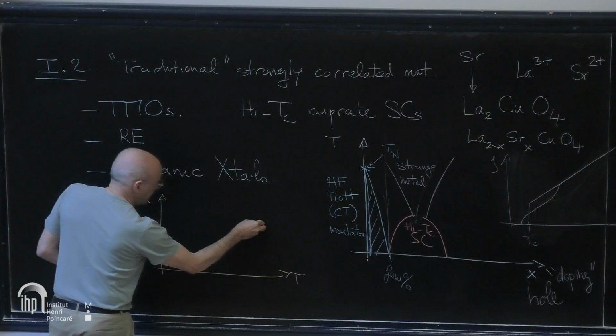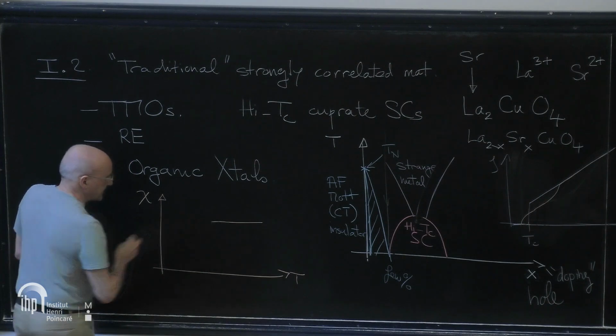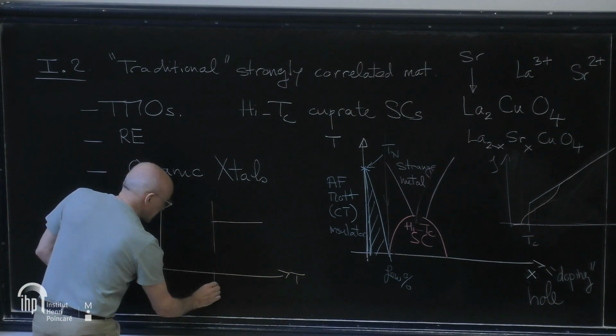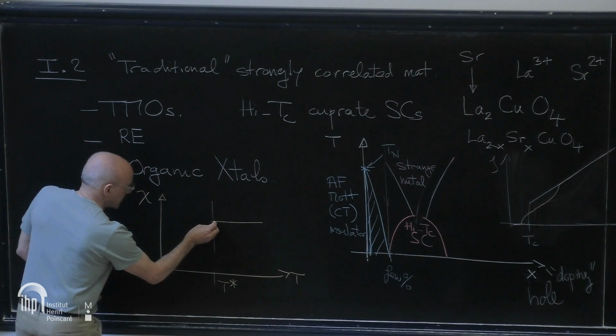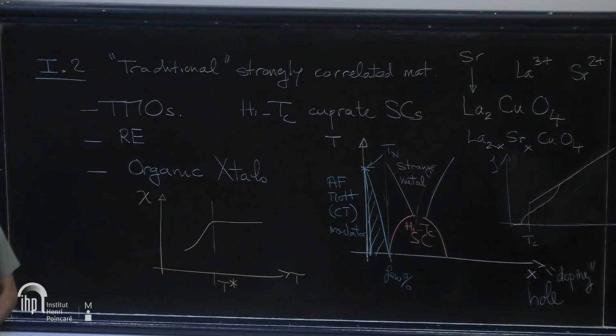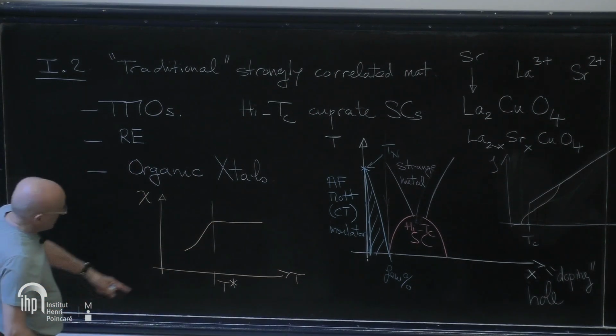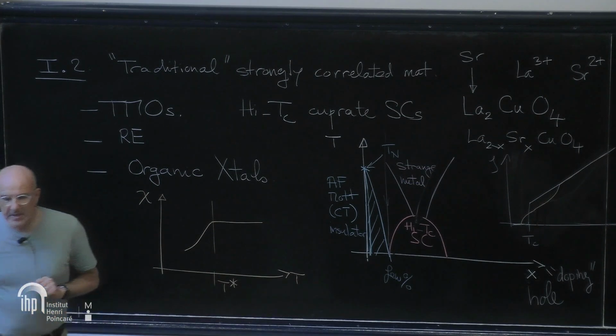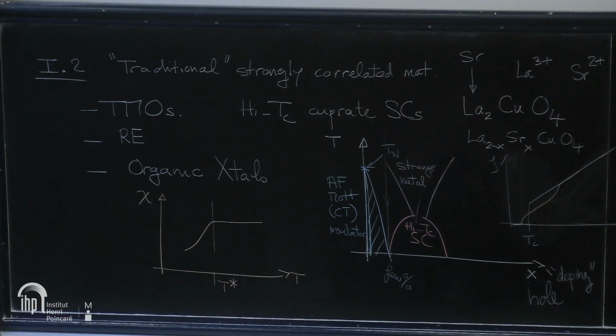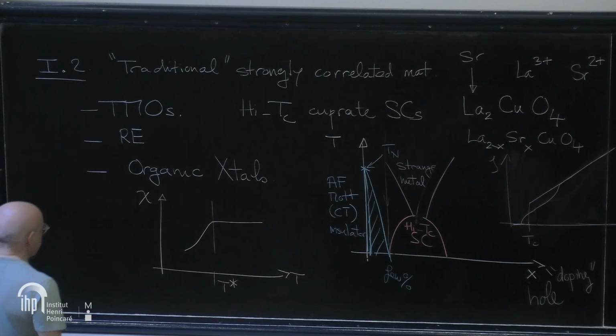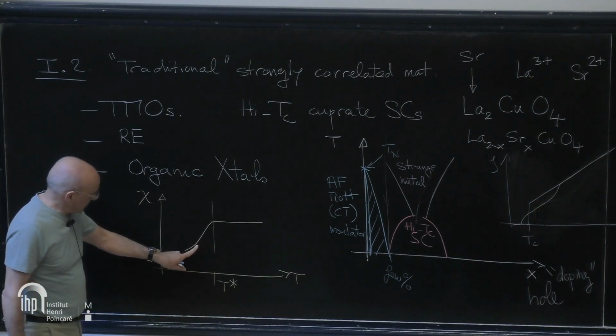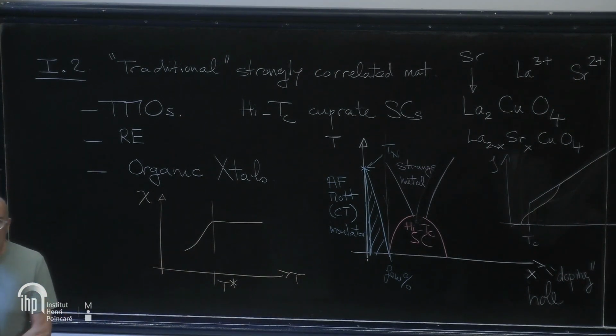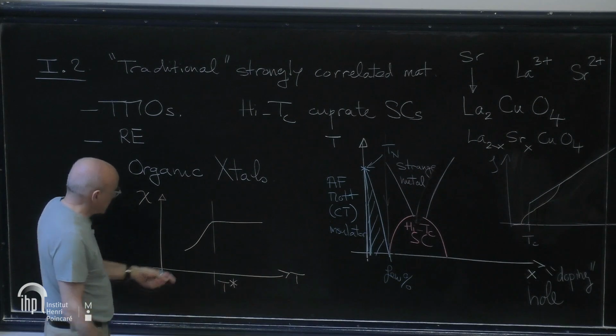Well, in this regime, that's not what is seen. What is seen is that the susceptibility is sort of constant at high T, but below a certain temperature that we call T star, it goes down. So susceptibility in, let's say, free fermions is related to the density of states of the system, right? So if you interpret this phenomenologically very simply, this means that you are sort of losing density of states. So you are losing the ability to excite the system. The density of excitations becomes lower than what it should be.